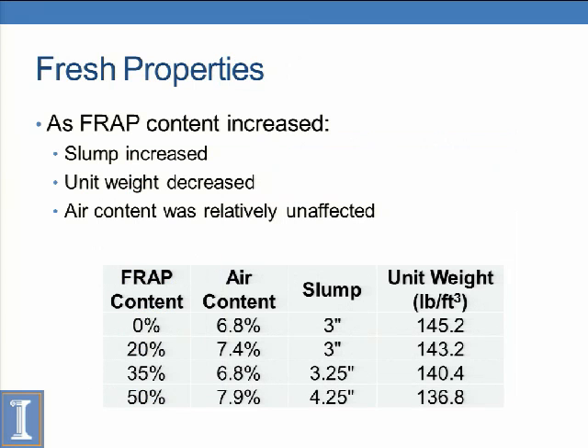So now the fresh properties, the workability of fresh concrete. Pretty much what we found is that the slump increased with our increasing FRAP content. Interesting thing about that is we reduced the water reducer dosage as we increase the FRAP content. So typically with a normal mix, if you reduce water reducer content, your slump should go down. So we had an increase in slump despite reducing water reducer. So that was an interesting find. Unit weight also decreased, which is not surprising since there's an asphalt layer on that aggregate, which has a lower specific gravity, so of course the unit weight will go down.